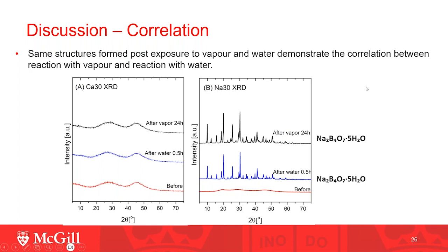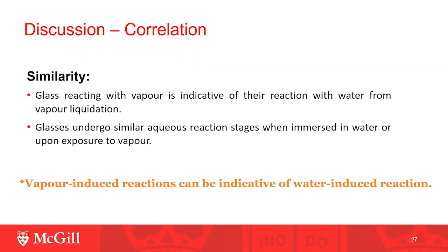The same crystal formation post-exposure to water and vapor for both glasses demonstrates the correlation between the reaction in the water and the reaction in the vapor. This means aqueous reaction in the water and in the vapor appear to occur by a similar mechanism. Actually, the glasses reacting with vapor is the glasses reacting with the water from vapor liquefaction. Therefore, the glasses undergo the same aqueous reaction when immersed in the water and exposed to vapor.